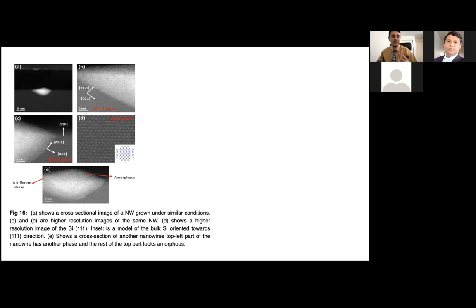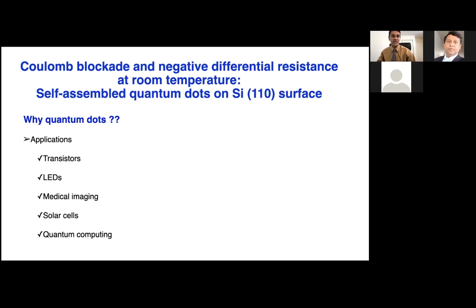Then after this, we wanted to get longer nanowires, at least up to the micron level. So we changed the annealing temperature, we changed the annealing time, we did lots of things, but we couldn't get elongated, long nanowires. So finally we tried coverage, to see how coverage affects the surface. That is how we landed on quantum dots.